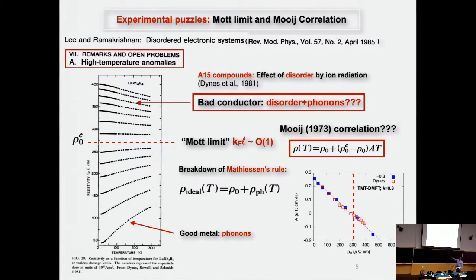How do we understand this regime where something happens? Now you may say maybe it's just complicated, non-universal. What Mooij in the 70s pointed out is that in this regime there's a rather systematic behavior. He said that resistivity in this high temperature regime is a linear function of temperature, but the slope changes sign and exactly vanishes around the Mott limit. But the slope and the intercept are correlated in such a way that if you extrapolate these curves linearly, they will all cut at one point. So this is called the Mooij correlation, and it has been found initially in some materials.